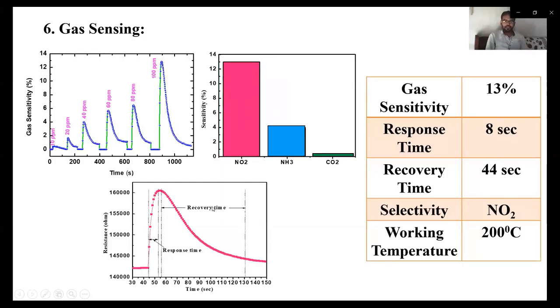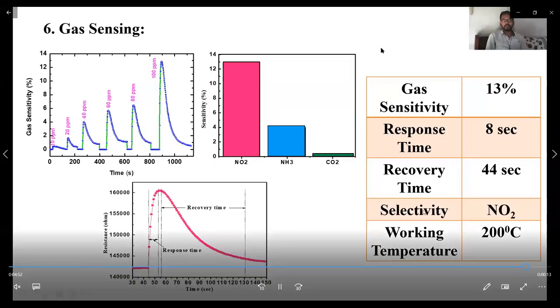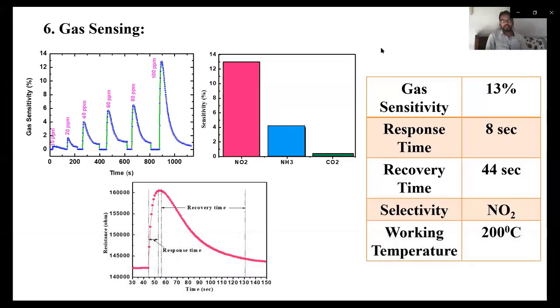This graph is the calculation for recovery time and response time. The response time and recovery time are 8 seconds and 44 seconds, which is good in comparison with other reported research papers. The working temperature for this gas sensing is 200 degrees Celsius. Overall, the prepared vanadium pentoxide showed good gas sensing performance.